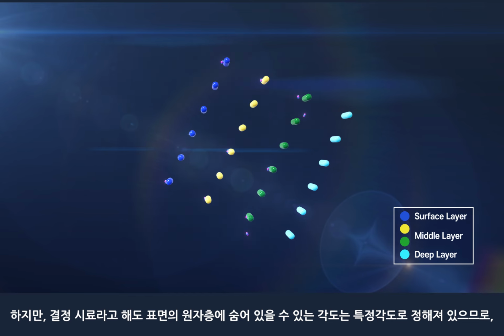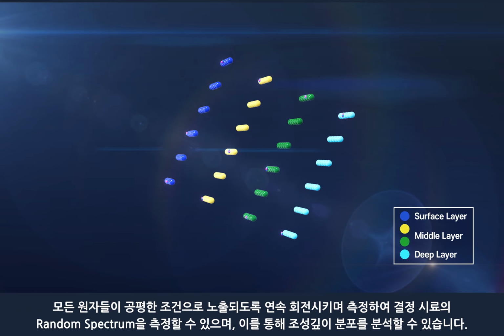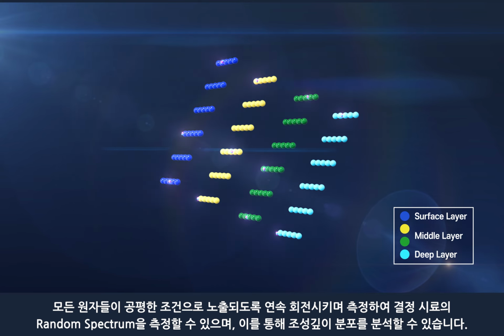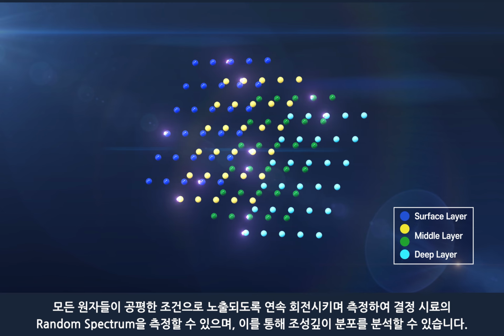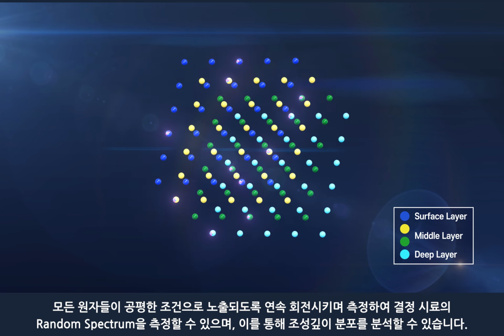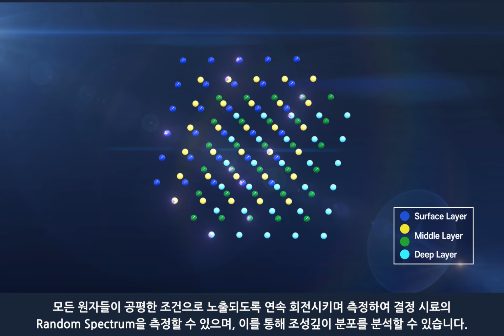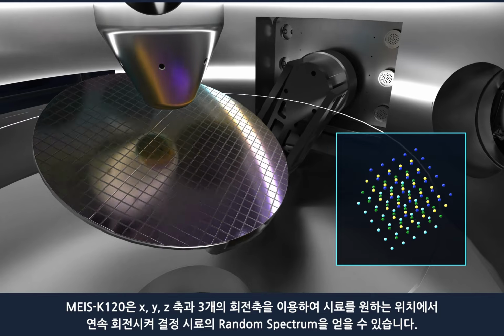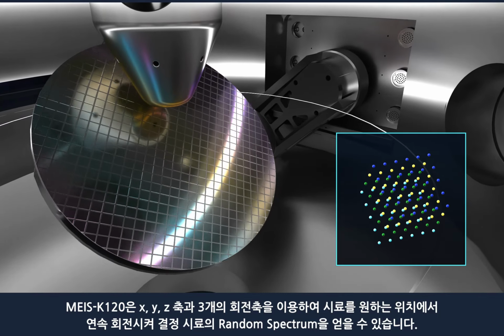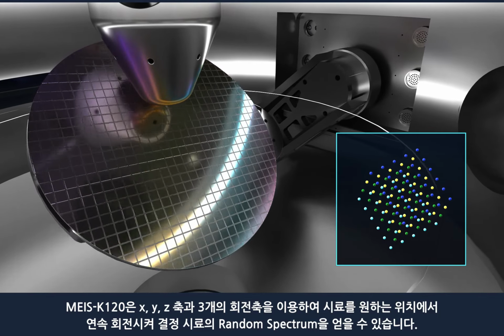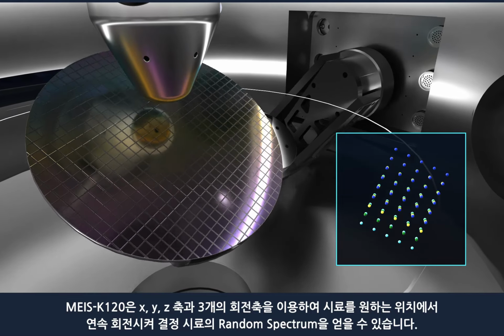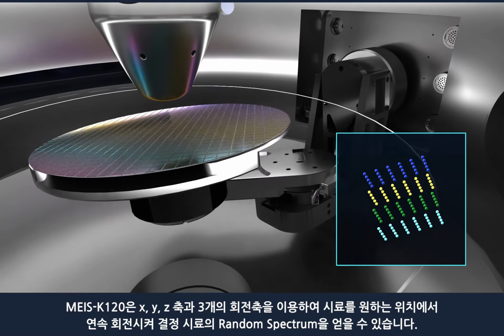However, even for crystal samples, the angles at which the atoms of the crystal can hide are limited to a few angles. Therefore, if the crystalline sample is continuously rotated at a certain angle, all atoms are exposed to the incident ions with the same probability. Thus, a random spectrum of the crystal sample can be obtained. MEIS K120 can acquire a random spectrum of a crystal sample at a desired position by continuously rotating using the X, Y, Z, and 3 rotation axes.